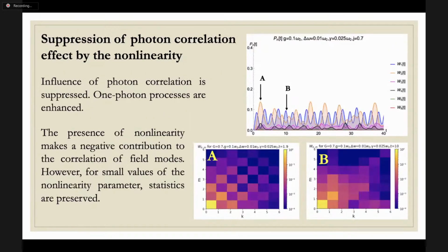Next, if cross-phase modulation is taken into account, single photon processes are enhanced since the effect of photon correlation is suppressed, and the presence of nonlinearity makes a negative contribution to the correlations of field modes. So synchronicity is broken. However, for small values of the nonlinearity parameter, the photon number distribution in two modes discussed above can be observed.